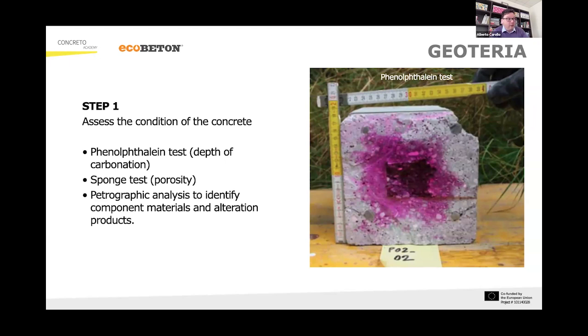So when you spray, very easy, you spray this product, and where it is purple means the concrete still has a very high pH, so the rebar are protected. Where it is clear without any coloring, the rebar are not protected. And you see in this picture, we got 4 rebars, and all 4 of them are outside this one.